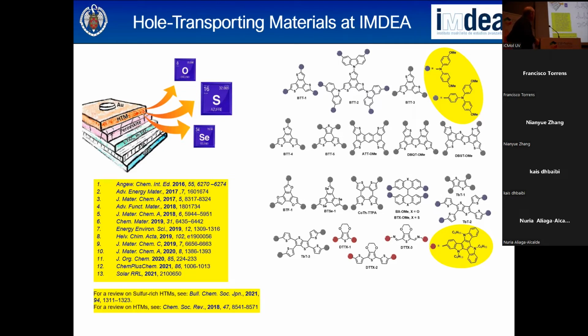So you can see that the number of sulfur is 3. 3 is also here, but it's not the same because here are isomeric structures. 2 sulfur atoms pointing at the same side is not the case like here, or we have increased the number of sulfur atoms, 4, 5, 6 sulfur atoms, and so on. We also use different heteroatoms, oxygen, selenium, and so on, and also some simple central cores as well. What is interesting to mention here is that the presence of sulfur in these molecules is very good because it improves the charge delocalization and the intermolecular interaction.